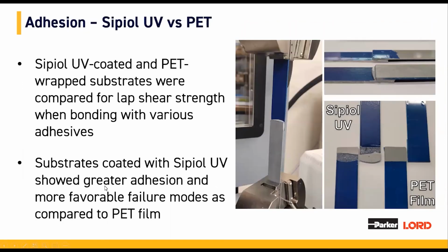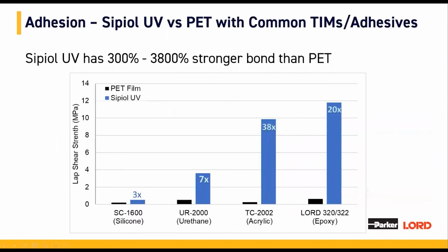Sipiol UV coated substrates and PET wrapped substrates were compared for lap shear strength when bonding four major classes of adhesives used in battery technology. Not only did the substrates coated with Sipiol UV show greater adhesion, Sipiol UV also showed more favorable failure modes as compared to PET film. This is demonstrated in the image on the bottom right, showing Sipiol UV coated substrates achieving cohesive failure at the bond line compared to the PET film, which exhibited adhesive failure in most cases.